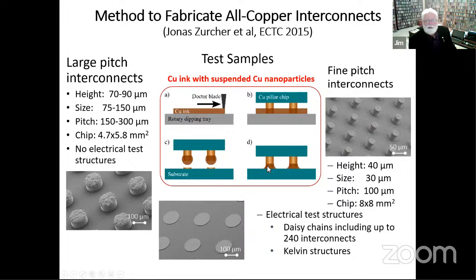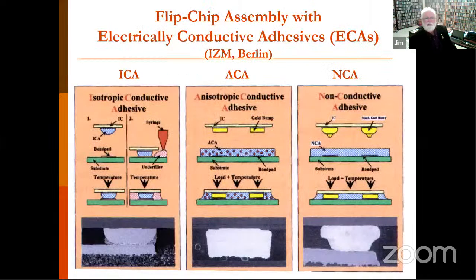This is copper nanoparticles sintered and a copper contact. So there's no interdiffusion or alloying possible in the system. So this is very stable. So I mentioned electrically conductive adhesives. These divide into isotropic conductive adhesives, where these are typically an epoxy loaded with silver flakes and a little powder, which assists the contacts in the flakes when the material is cured. And so it is cured under temperature and pressure.